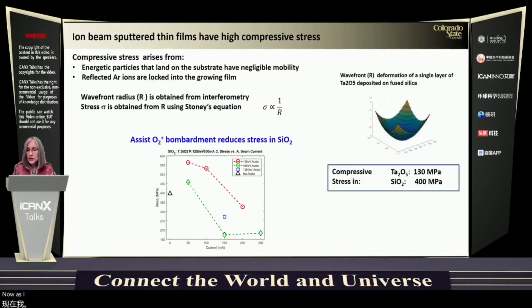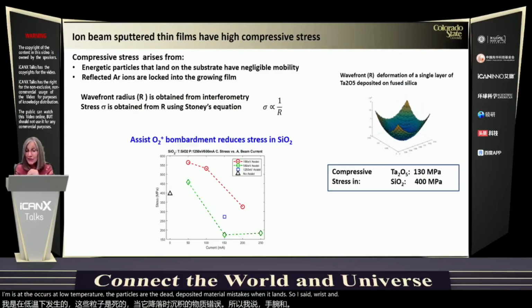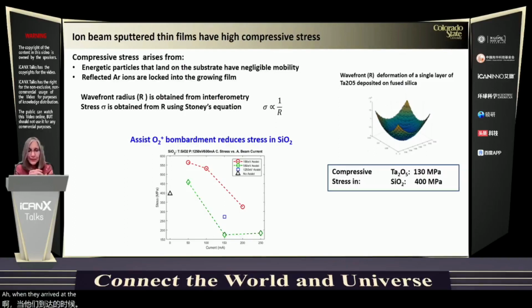Now, as I mentioned, the growth process occurs at low temperature. The deposited material sticks where it lands. Furthermore, the particles do have an energy when they arrive at the substrate. As a result of that, the films have very high compressive stress. The way that we assess the stress in the thin films is by interferometry. We measure the deformation of the wavefront of the substrate, as I show here, in which we coat single layers or multi-layers. And then we use the Stoney equation to relate wavefront deformation to stress.